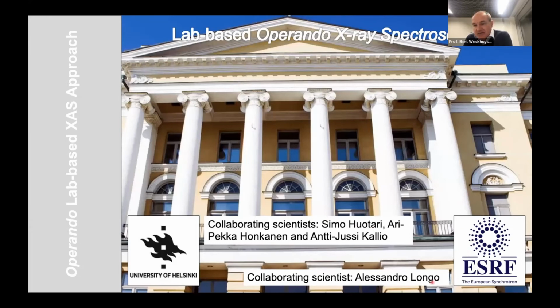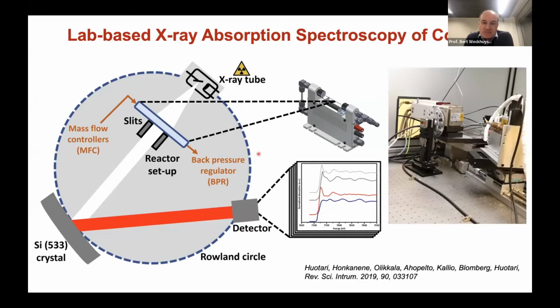And for references, I show you some ESRF data which we collected in Grenoble. The setup is the one developed there. You can here find the Rowland circle. And here you see the X-ray tube. And here you find our in situ cell, which I already described before. With this in situ operando cell, you can determine what is happening. And you have a back pressure regulator, which allows you to measure at high pressures.